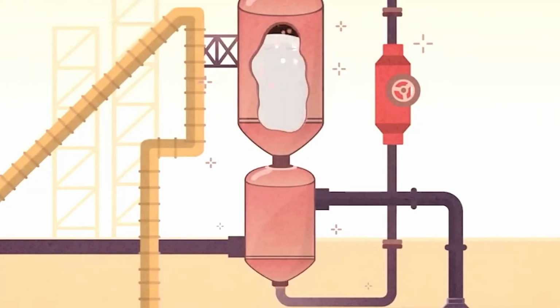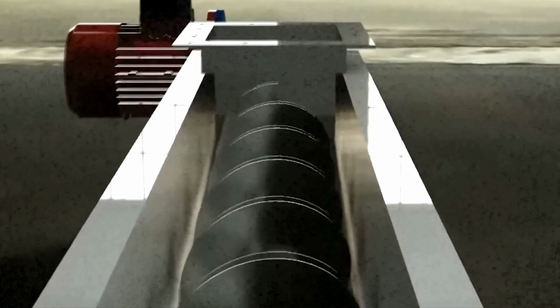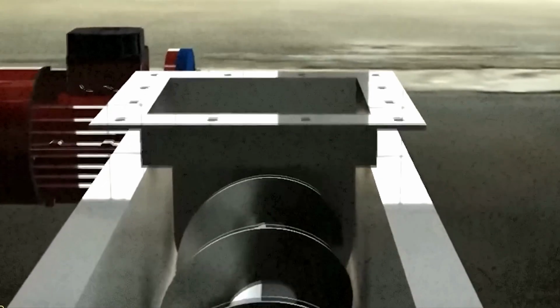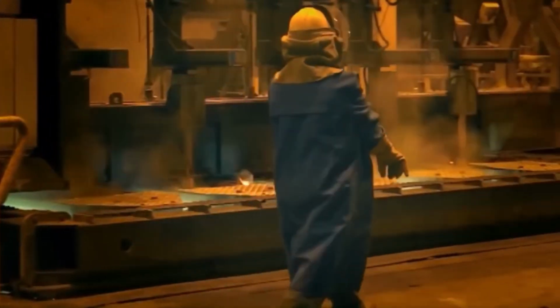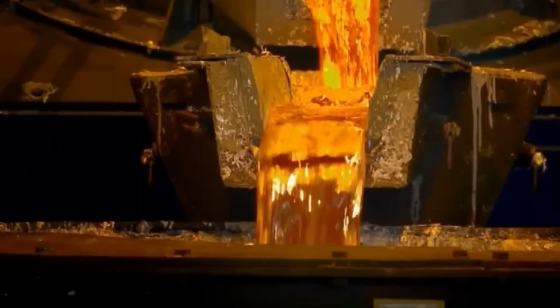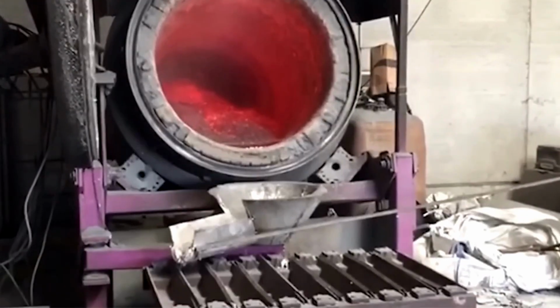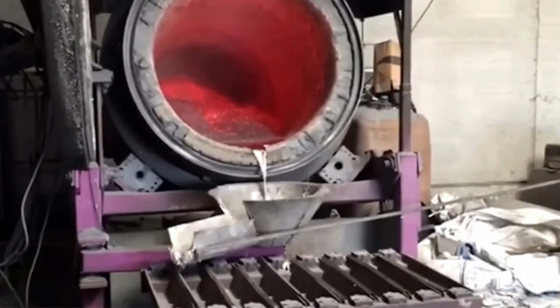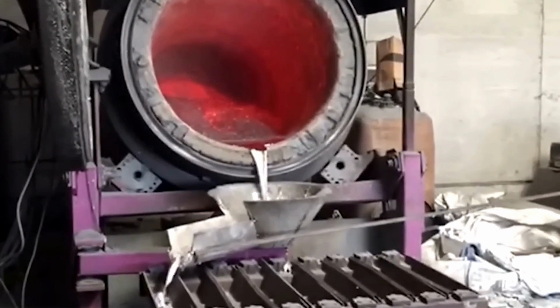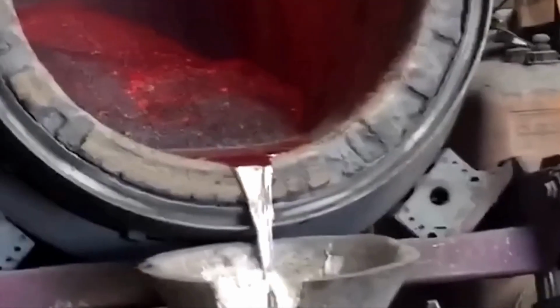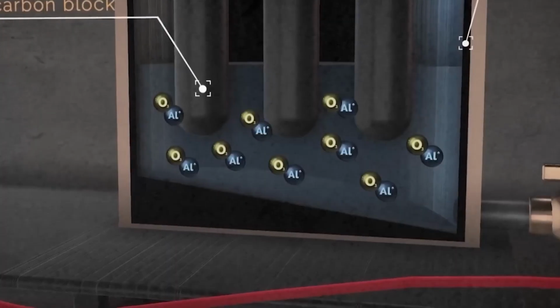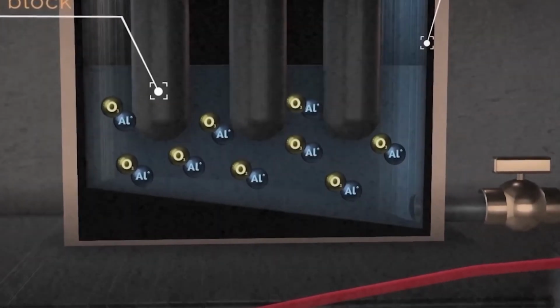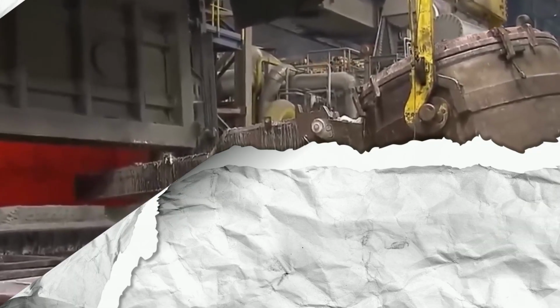A screw conveyor continuously moves the alumina crystals into a rotating cylindrical kiln that is slightly tilted, allowing gravity to help transport the material through it. Inside, the kiln reaches temperatures of 2000 degrees Fahrenheit, 1100 degrees Celsius, driving off the water molecules and leaving behind dry anhydrous alumina crystals. These crystals then pass through a cooling system, preparing them for the next stage, smelting.